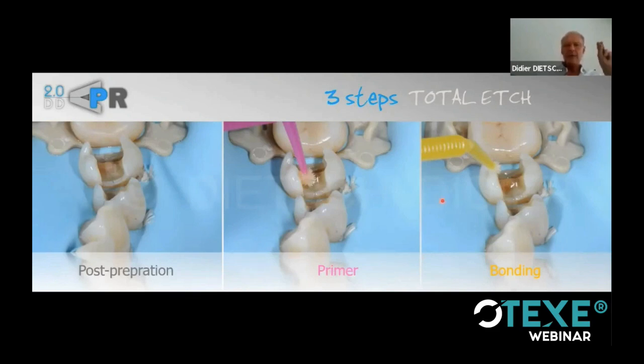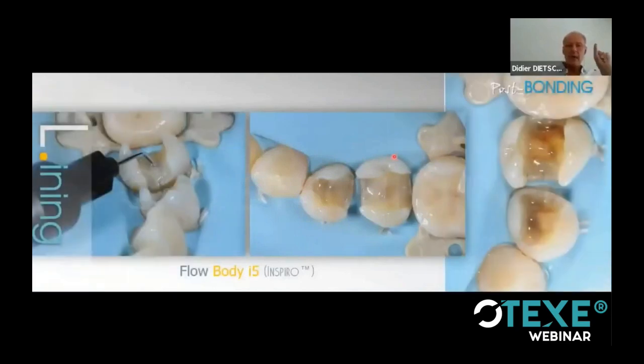So my preference is three-step total etch, or as an alternative, which I like very much also, two-step self-etch, but always separate priming and bonding. I think this is really one of the keys. What we understand today about long-term stability of adhesion relates to the use of a mostly hydrophobic adhesive interface.